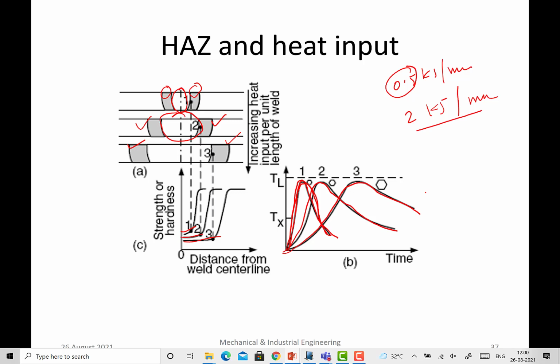You can see when the thermal cycle is corresponding to low heat input, your grain size is very fine because high temperature retention period is low. When heat input is more, high temperature retention period is longer. That is what you can see. And with further high heat input, the high temperature retention period is further longer, even for the same peak temperature. Okay, so there will be enough time for diffusion to take place at a higher temperature and contribute towards the coarsening of the grains, towards the softening or development of the soft phases due to the lower cooling rates, higher temperature retention for longer time.